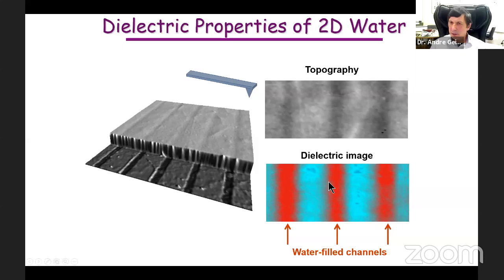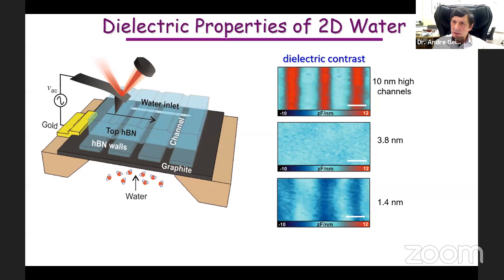What you see on the dielectric image are very bright red spots, showing that here there is some medium, actually water, with a large dielectric constant. And then we do the same for different heights of the channels. For a macroscopic channel, 10 nanometers high, we see bright contrast, water here.